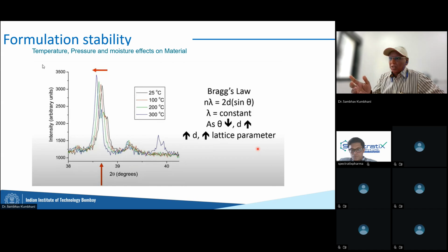Anyway, this is a great example of what happens to a substance if it is heated, and you constantly measure the XRD while you are heating. As you heat the sample, in principle, the spacing between the lattice planes is increasing. And as the d value goes up, theta goes down. And this is your theta. So the black line over here, the outside one, is at room temperature. And then you are heating it, so your spectra is shifting towards the left. If your spectra shifts towards the left, that means the d spacing is going up. That means your structure is becoming weaker and weaker.